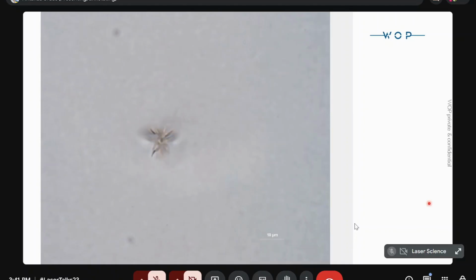So again, compared to what we saw with the bad shaping of the beam, here you can see what we can make with quite proper and very specific shaping of the beam, in polarization profile and energy distribution along the beam. You can see that this crack structure inside the volume is not very regular, but it can be considered almost the same size along all the path. And this gives us quite a good result.